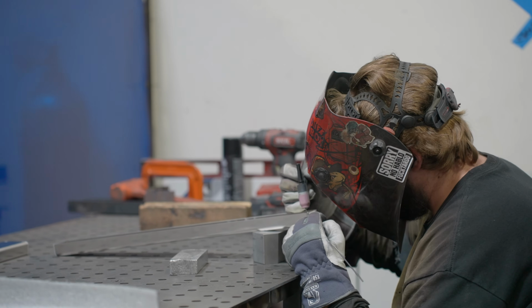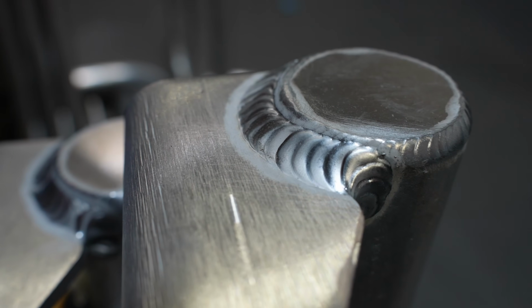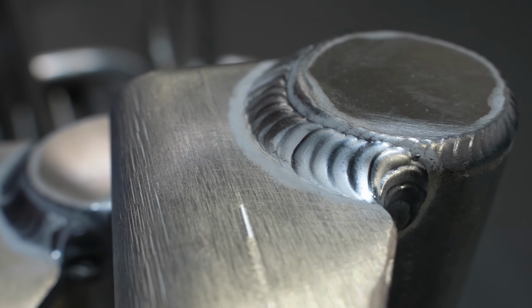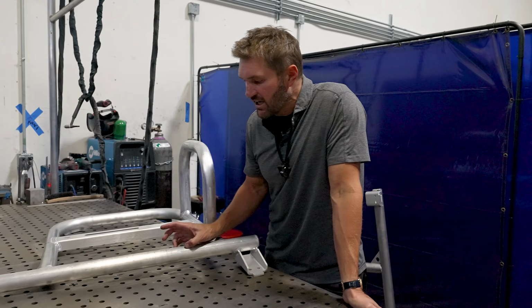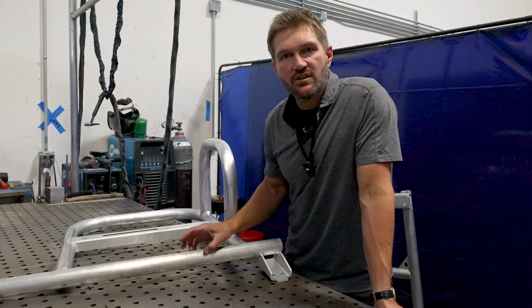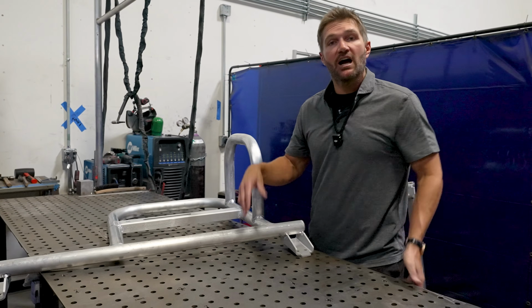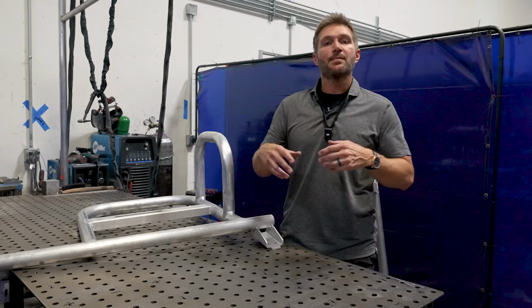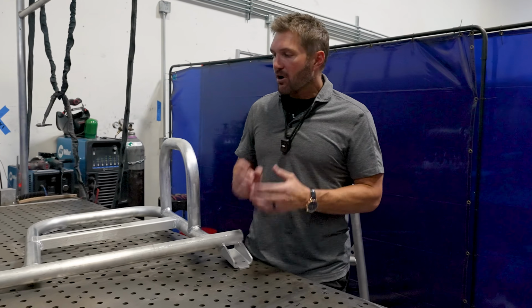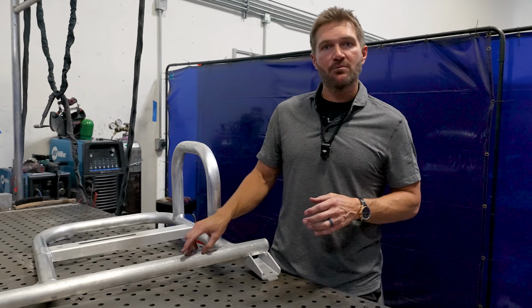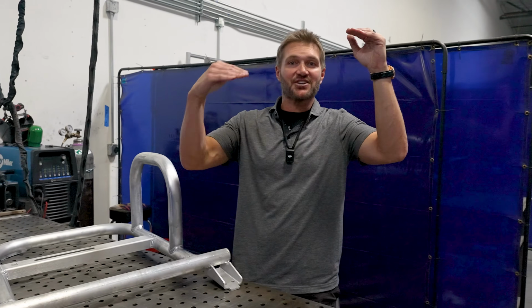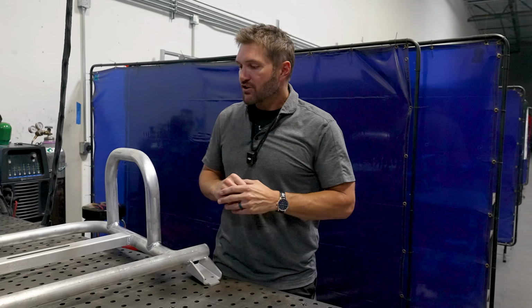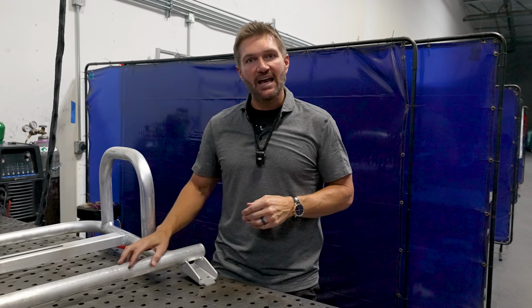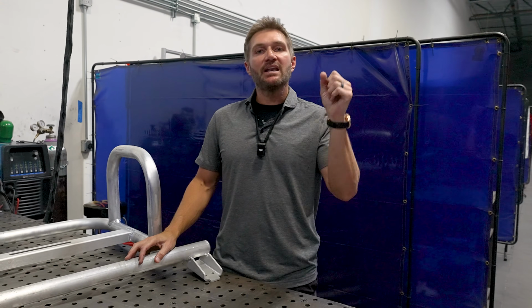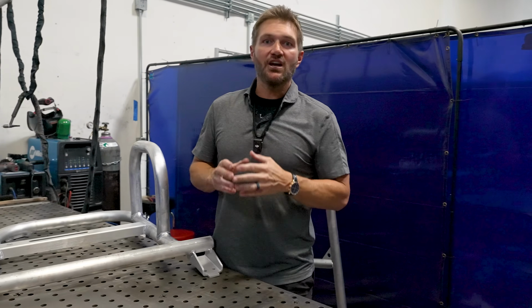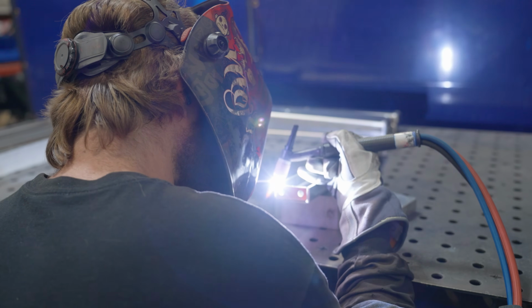Aluminum is a unique metal. It's very soft. It has a low melting temperature. It also gets this oxidation layer on it. And the thing about the oxidation layer is you can't weld if the oxidation layer is there. So the oxidation layer has to be burnt off before you can weld the material. The problem with that is that the oxidation layer of aluminum is at a higher melting point than the actual melting point of the aluminum. So that means that you have to burn off the outer layer of oxidation, but not vaporize the aluminum underneath. It's very, very difficult, and it takes a lot of practice.